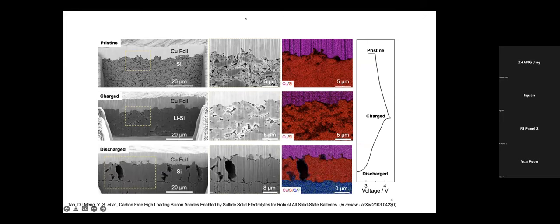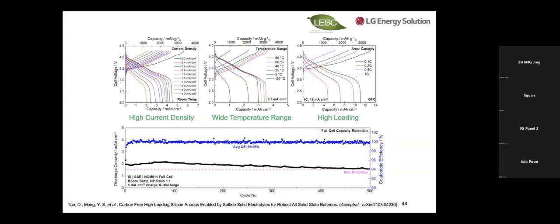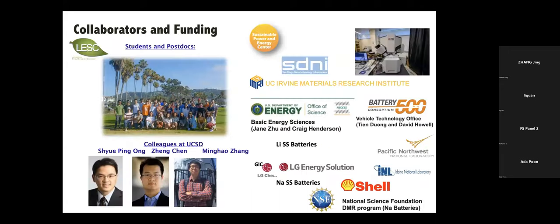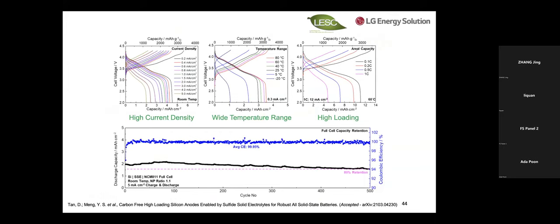I think everybody can read those in detail, but I just want to point out, we start with this micron silicon, we lithiate at high pressure, and the whole lithium silicon will be densified and amorphized. And when you take lithium out, today we know there's about 20% of the lithium remaining in this anode, and you form that kind of a scaffold. The volume change is only the first cycle volume change. And then subsequent cycles are extremely stable, which allowed us to go for 500 cycles with 80% retention. So this work showcased that the SEI stability in the silicon is actually outstanding with this sulfide solid electrolyte.